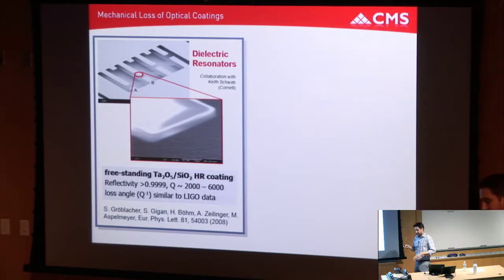The way that we sort of morphed this from the VCSEL world to the large bulk optics was, as Dahl said, I worked in this cavity optomechanics field. And again, I don't have time to go into the details there, but the idea was you could use the same basic laser cooling processes that you would use to cool trapped ions or atoms. You can take a mechanical resonator and cool an isolated mechanical resonance of that system in a detuned optical cavity. All I'll really say is the basic needs are you want high reflectivity, low optical loss, and very high mechanical quality factor. And here the high mechanical Q is sort of a filter, so it reduces the rate at which phonons leak from the bath into the resonator.